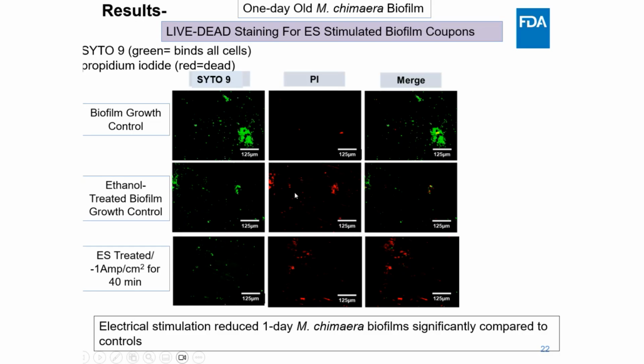On this slide, you see the image of three conditions. An untreated growth control is on the first panel over here on the top. The middle panel shows a 40-minute ethanol-treated control, as we wanted to test the chemical treatment compared to the electrical stimulation. And the third panel at the bottom shows a 1-day-old biofilm subjected to -1 amp current density treatment for 40 minutes. The merged image over here shows both stains overlaid, allowing us to visually assess the proportion of live versus dead cells within the biofilm matrix.